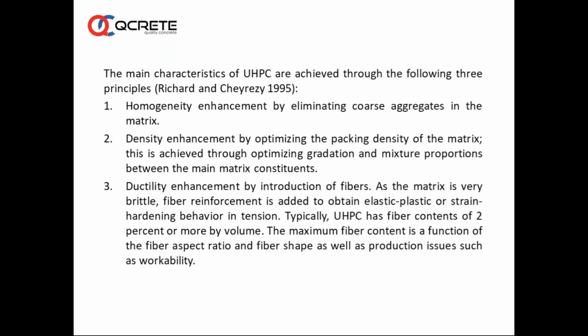Ductility enhancement is done by introduction of fibers. As the matrix is very brittle, fiber reinforcement is added to obtain elastoplastic or strain hardening behavior in tension. Typically, UHPC has fiber contents of about 2% or more by volume. The maximum fiber content is a function of the fiber aspect ratio and fiber shape, as well as production issues such as workability. So addition of fibers, basically steel fibers, brings the other dimension in the case of UHPC as far as ductility is concerned. There are cases where we find combinations of steel fibers and other fibers. We will talk about that.